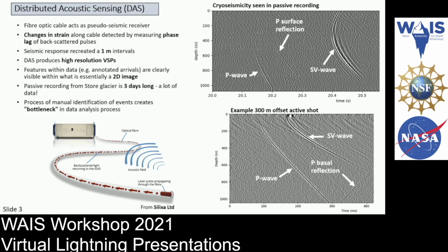The strain on the cable is averaged over a predefined length, known as the gauge length, which gives the effective spatial resolution of the cable, as wavelengths shorter than this cannot be detected. However, the signal is recreated with pseudo-samples every meter, which use this average seismic response from within a 10-meter wide window, the gauge length, in which the pseudo-sample is centered. So DAS is able to produce a high resolution vertical seismic profile, or VSP.